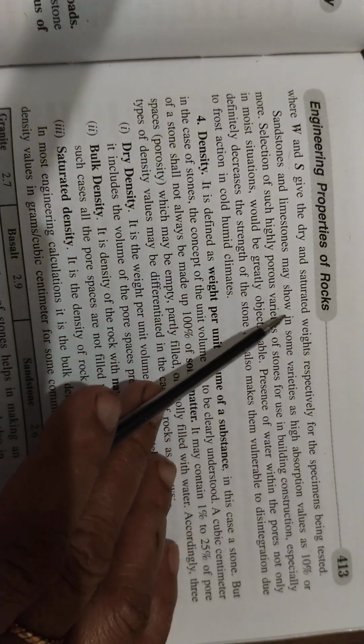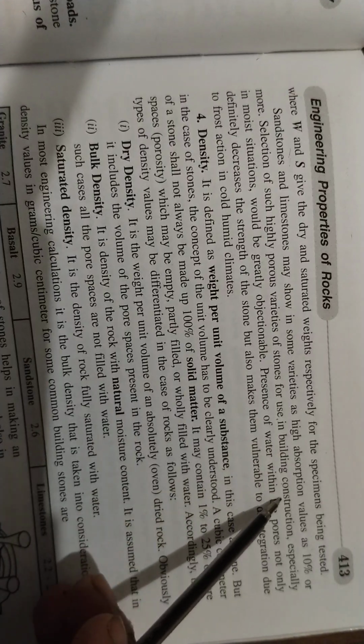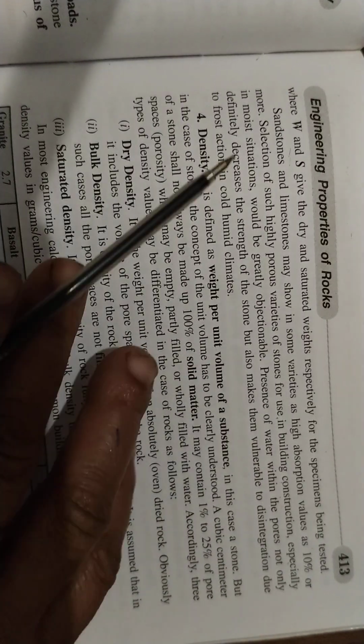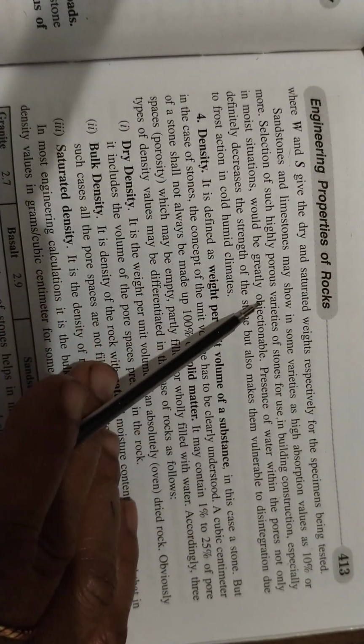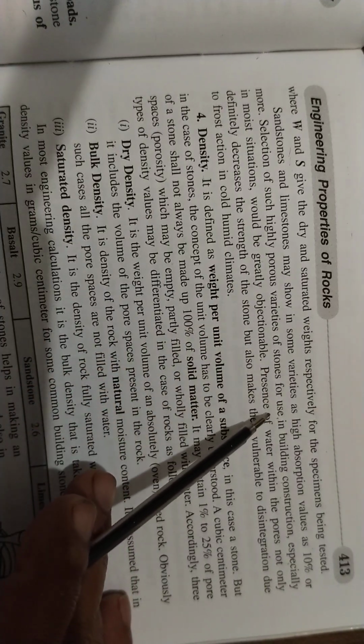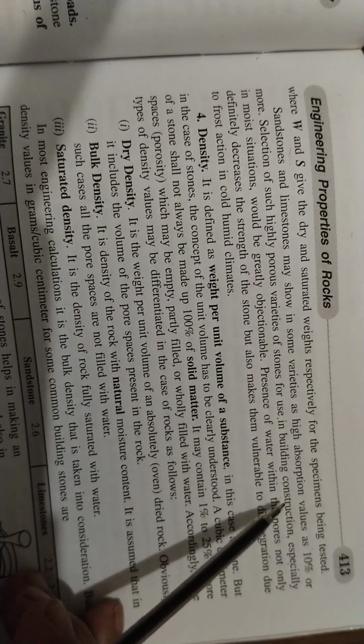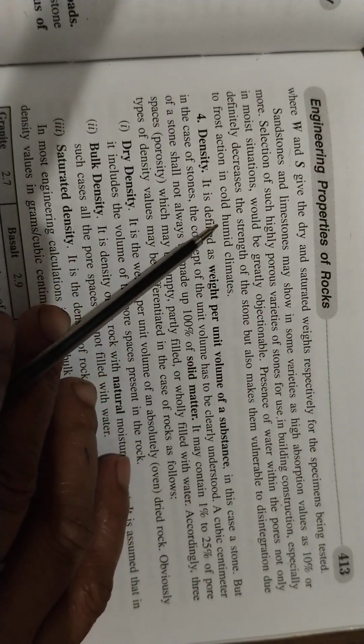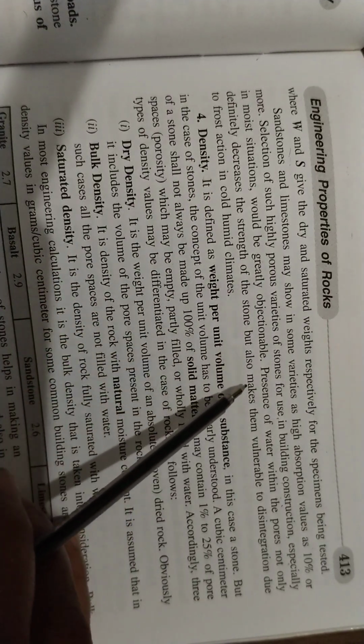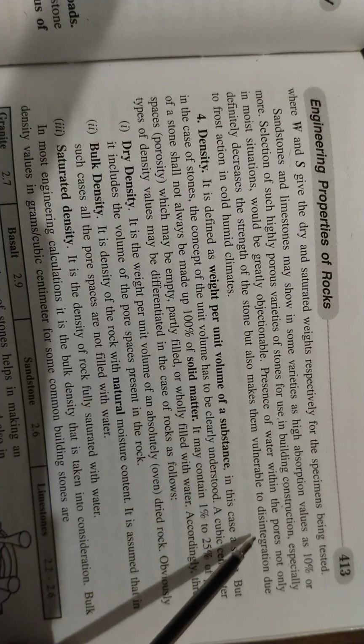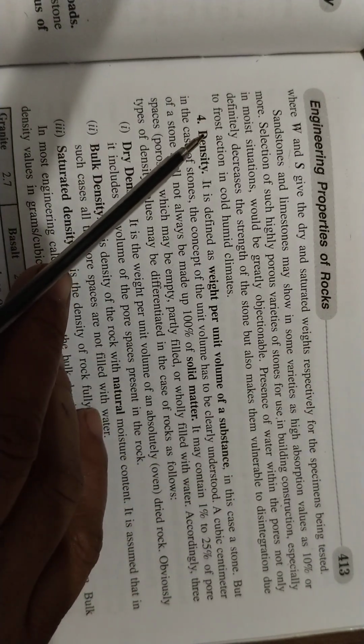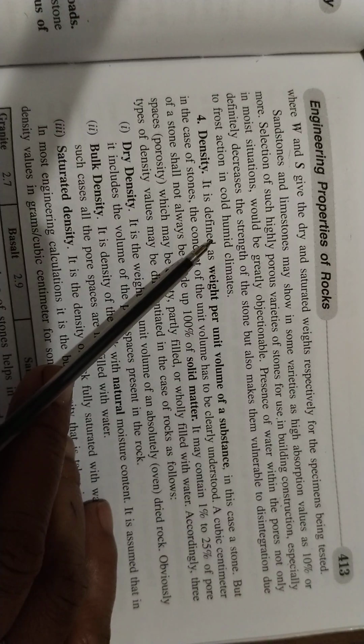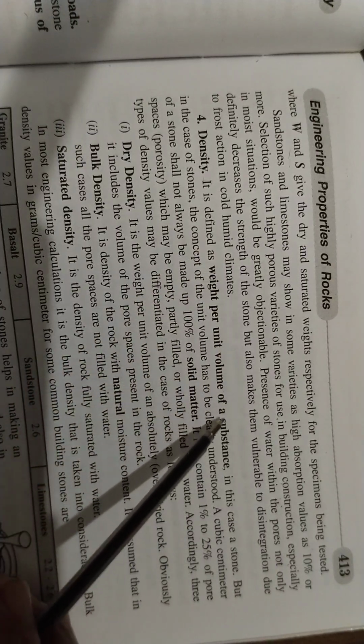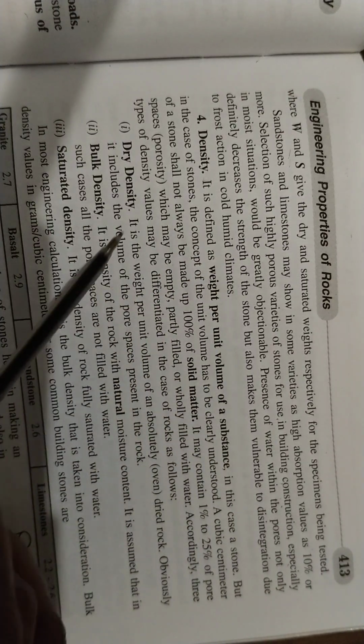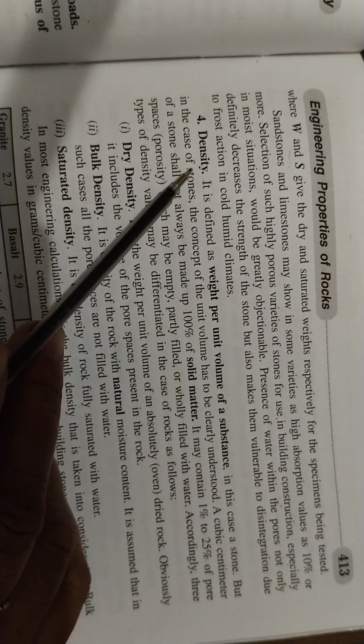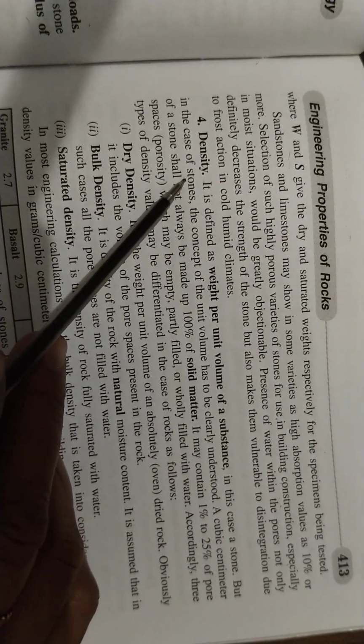Sandstone and limestone may show in some varieties as high an absorption value as 10% or more. Selection of such highly porous varieties of stones for use in building construction, especially in moist situations, would be greatly objectionable. Presence of water within the pores not only definitely decreases the strength of the stones but also makes them vulnerable to disintegration due to frost action in cold humid climate.